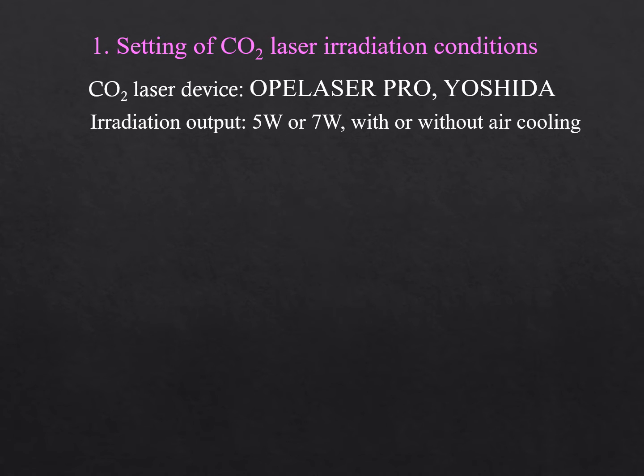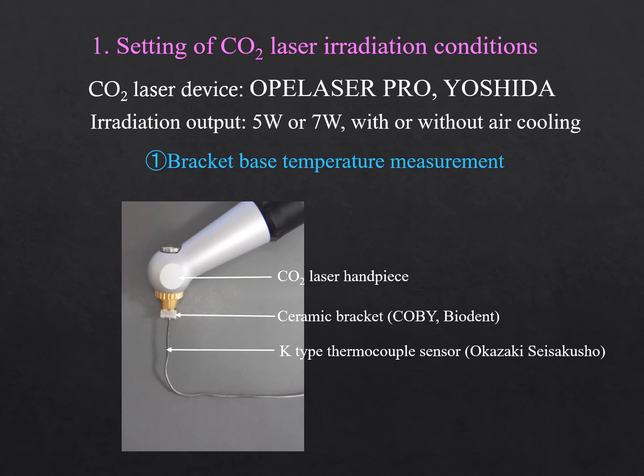In this study, Yoshida's OPELASER PRO is used as a CO2 laser device. Its wavelength is 10.6 micrometers, continuous wave, and irradiation output is 5 and 7 watts. In order to set the appropriate CO2 laser irradiation conditions, the temperature rise in the bracket base was measured with a K-type thermocouple sensor in contact with the bracket base when the laser irradiation was performed. The temperature increase in the pulp chamber was also examined when the bracket base temperature rises above 80 degrees.